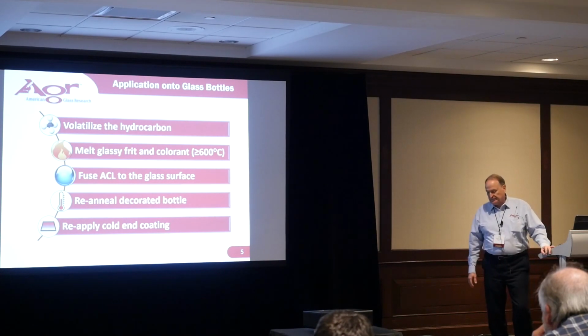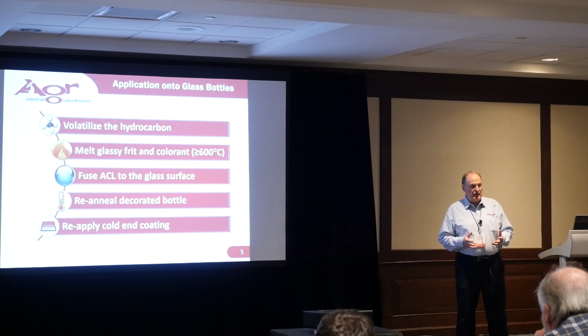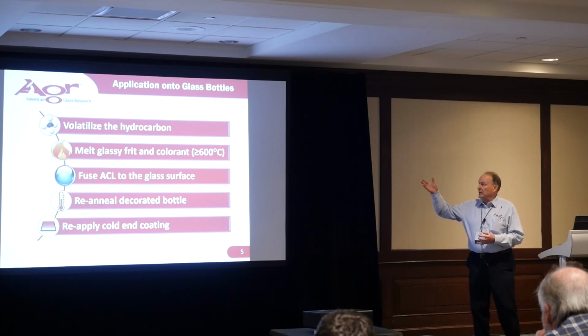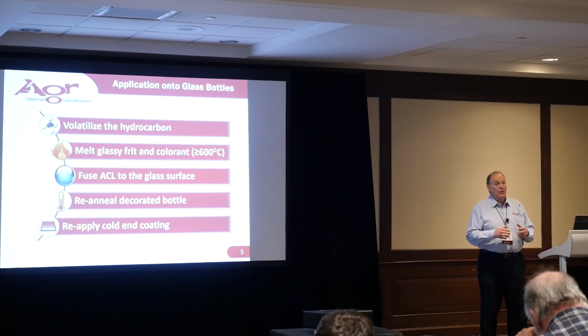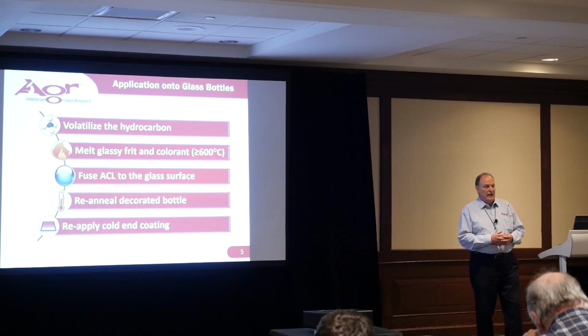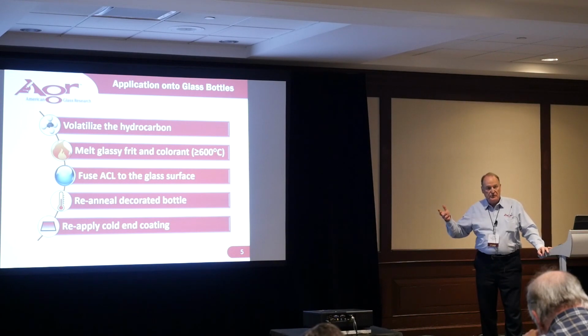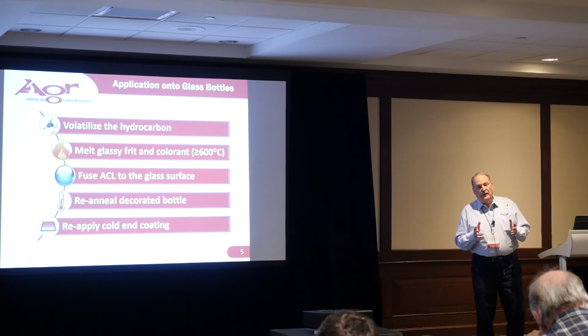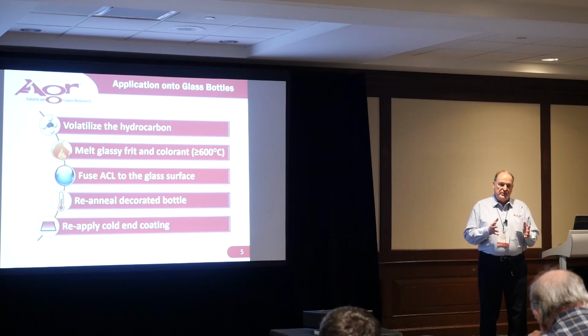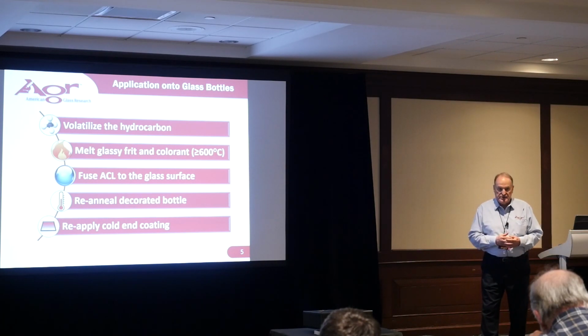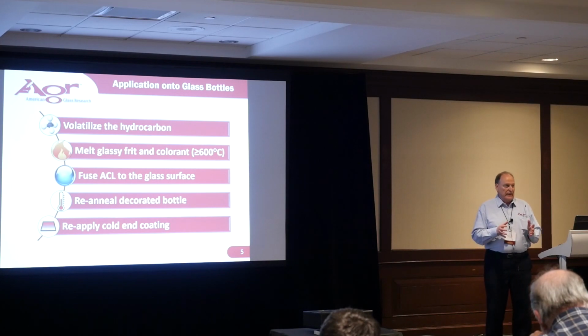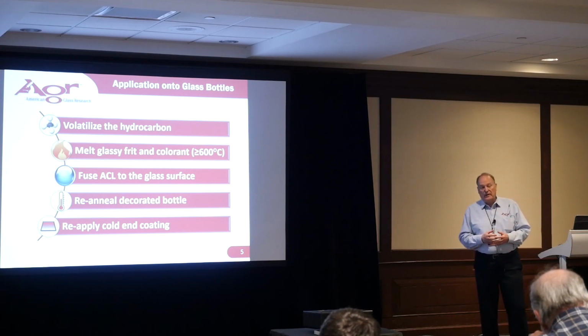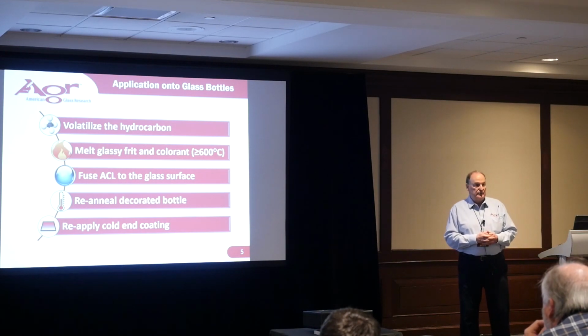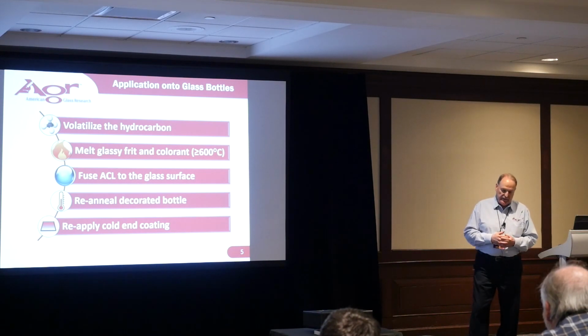Now we have a slight dilemma. The annealing point of soda lime silica glass containers is about 550 degrees centigrade. And by going up to slightly above 600, we are now well above the annealing temperature. And so once the material has been fused, molten, and we begin to cool the container, we have to be very careful about the cooling rate. It has to be controlled by the thickness of the glass container itself. And so the rate of cooling has to be within certain boundaries, or we would end up destroying the annealing state of the container. And that could be a problem, and I'll explain that in a few minutes.